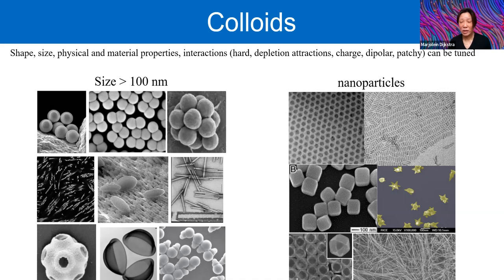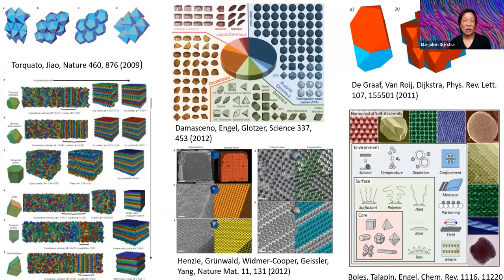One can make them from different materials: semiconductor particles, metallic particles, plastic particles, and so on. And one can even tune the interactions of all these particles, from hard, excluded volume-like interactions, towards depletion attractions, charge, soft repulsive interaction, dipolar interaction. One can even make these particles patchy in such a way that one can program the self-assembly in the surface patterns of these particles. This explosion of colloidal building blocks has also been accompanied with a boom of simulation studies. There's great work by the Torquato group, the Glotzer group, also our group, Escobedo's group. They all studied the self-assembly of all these particles, different particle shapes. One can also coat the surface with forms of surfactants.